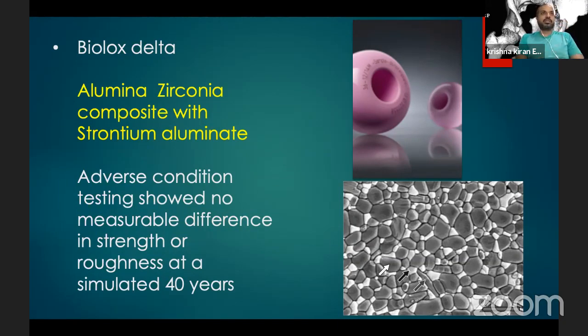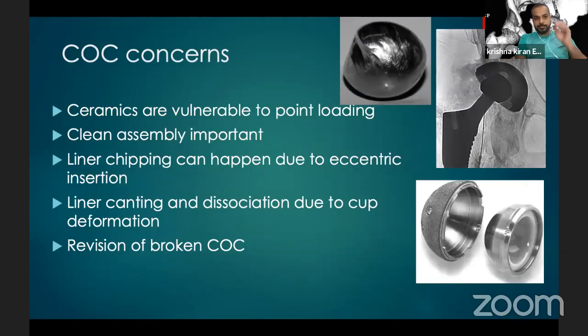The only way you can fracture it is if you malseat the liner and impact it into the acetabulum; it will break on the table. That's the way the liner can fracture. So you have concerns with ceramic on ceramic. They're vulnerable to point loading, especially if there is microseparation and edge loading because of component malposition. Clean assembly is very important.